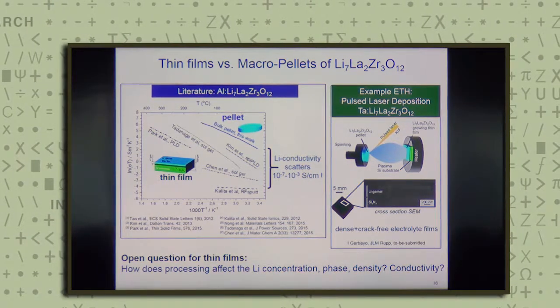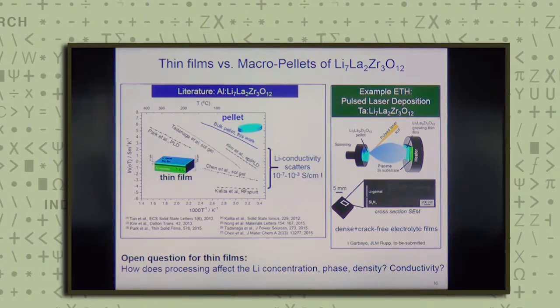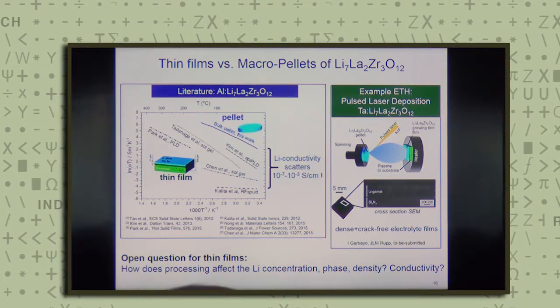So when we look now at what is out there on lithium garnet crystalline electrolyte films, then it's very shocking to engineer something here because you find a 4 order of magnitude scatter in the conductivity.